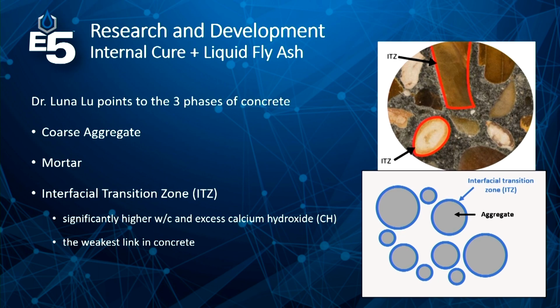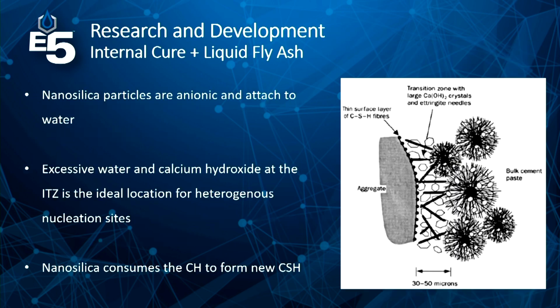But there's the interfacial transition zone, this ITZ, which is the immediate area around the aggregate where the cement paste bonds to that aggregate. And in this area is a significantly higher water to cement ratio and abundance of calcium hydroxide. She refers to the ITZ as the weakest link in concrete, the failure mode in concrete. Well, if you look at this diagram, what happens is that the bulk cement particles are kind of on the outside. They're the runt trying to get in, and they're too big to fit in the 40 micron space that's up close in the ITZ, where that excess water and calcium hydroxide is.